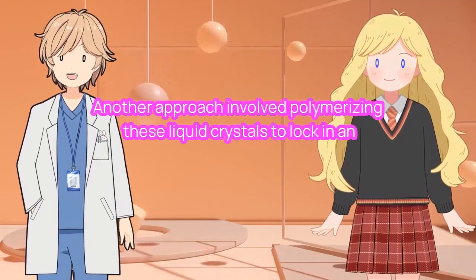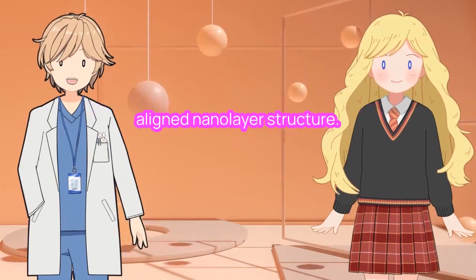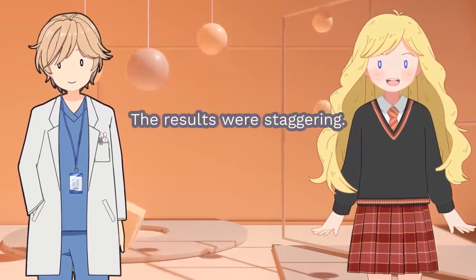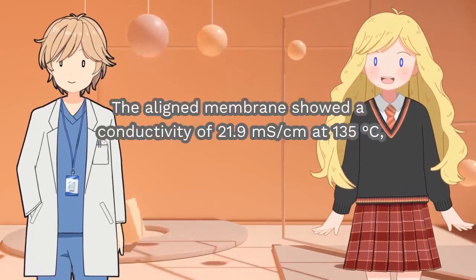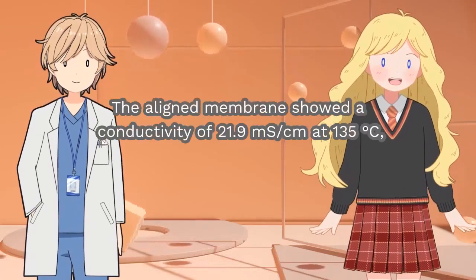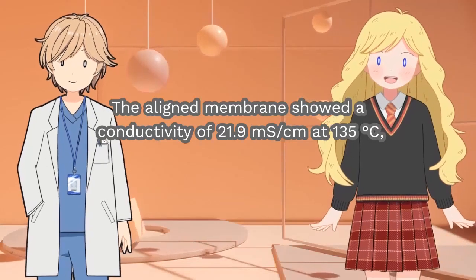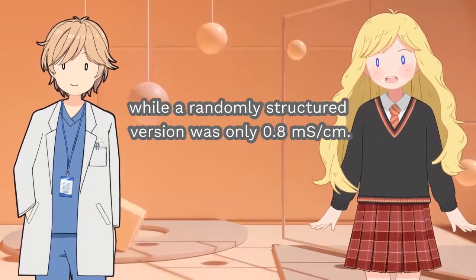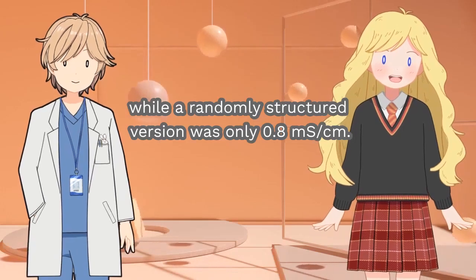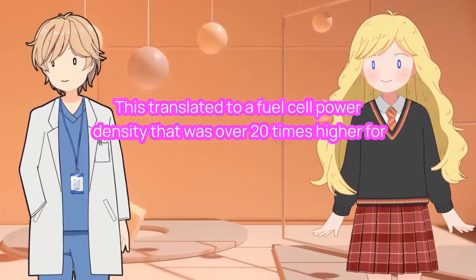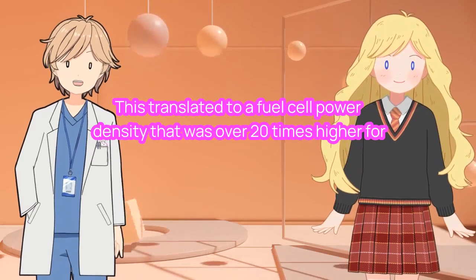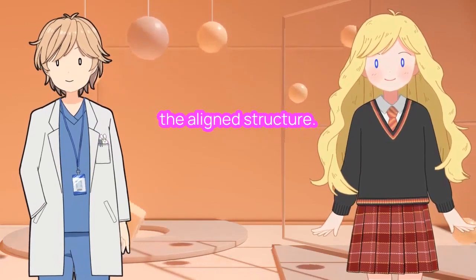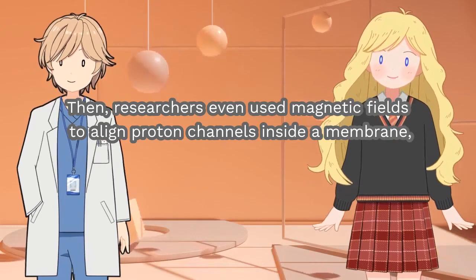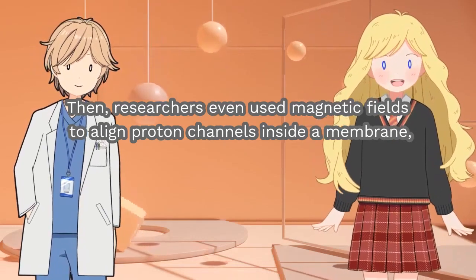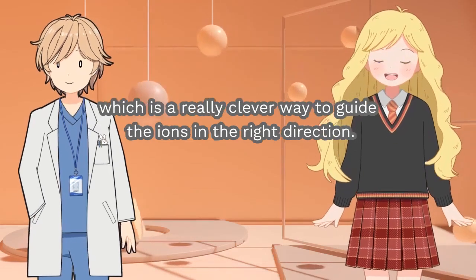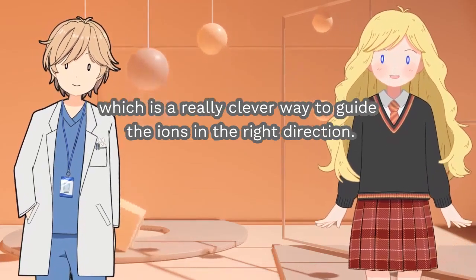Another approach involved polymerizing these liquid crystals to lock in an aligned nanolayer structure. The results were staggering. The aligned membrane showed a conductivity of 21.9 mS/cm at 135 degrees Celsius, while a randomly structured version was only 0.8. This translated to a fuel cell power density that was over 20 times higher for the aligned structure. Then, researchers even used magnetic fields to align proton channels inside a membrane, which is a really clever way to guide the ions in the right direction.